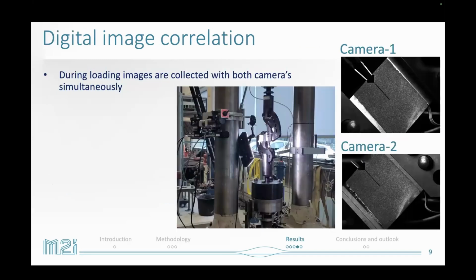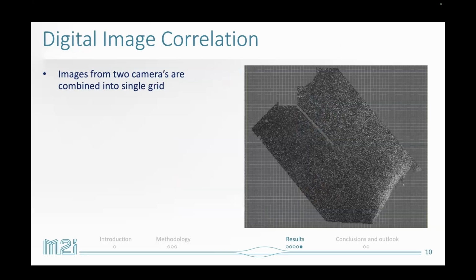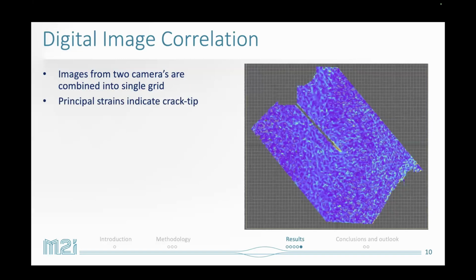And as I introduced, these were the results based on the fracture test, but we also did the digital image correlation test as already introduced in previous presentations. So the digital image correlation setup consists of two cameras, which simultaneously both take a picture. And using these pictures, you can combine them into a single grid, and then you can calculate all kinds of displacements and strains. And using the maximum principal strain, we can get an indication of where the real crack tip is, because there will be a jump in the calculated principal strains.